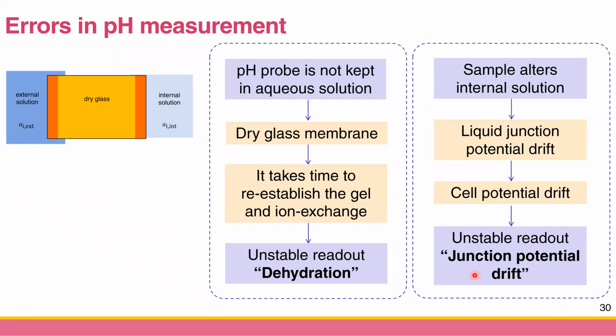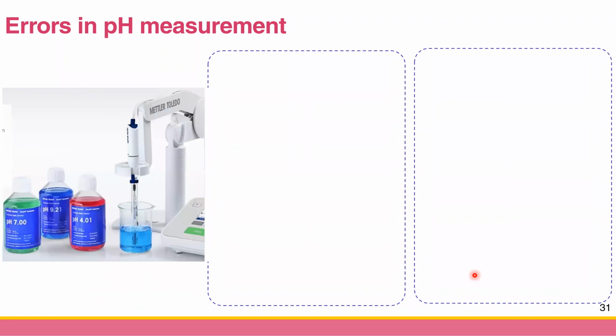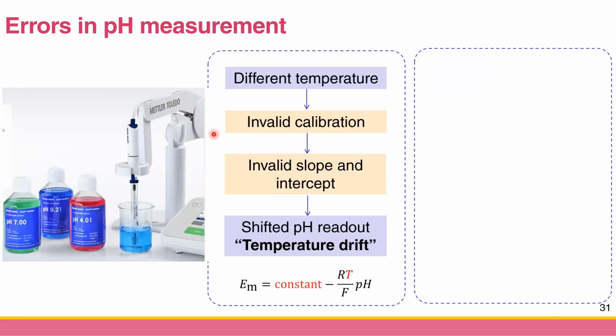The last two errors deal with the calibration. For example, if you calibrate your pH meter at one temperature, and then you take it out and measure the pH of your sample in another lab, which might not be air conditioned, which may be hotter or at a higher temperature, then this temperature change will shift your calibration curve. So your calibration curve that you get from your calibration is not valid anymore. Your slope and your intercept are not valid anymore. So your pH readout is not gonna be correct. And we call this error temperature drift.